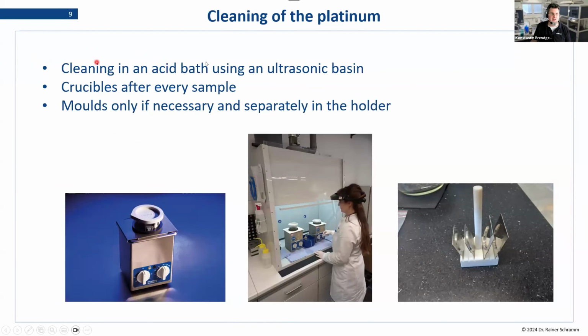When it comes to cleaning, the first question is, when do we clean each piece? Basically, we clean in the ultrasonic bath. There is more detail on the next sheet. We do that for the crucible after each fusion cycle. So after each fusion, we clean, then we do the next fusion. For the casting molds, that is usually not necessary. We usually leave them on the machine for, let's say, a work day, and we only clean them if there was an accident or if it's, let's say, a special aggressive sample.